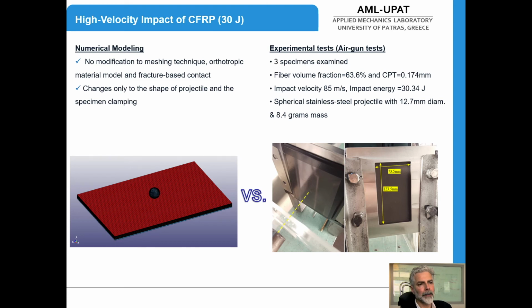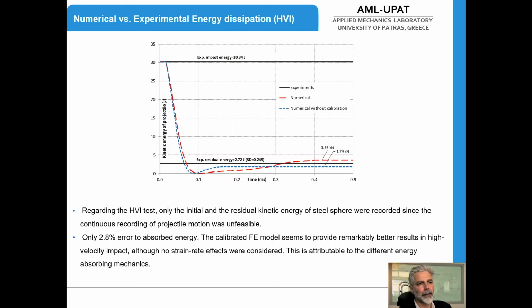This experiment has been made by using an air gun, and of course we have tried to simulate this experiment based on the same methodology that we earlier described, meaning that we use LS-DYNA explicit, we use 3D elements, we use the same optimized calibrated material parameters, and the only changes are the projectile and the clamping devices. Unfortunately, here we did not have the possibility to capture the contact force versus time plot. However, we can simulate the kinetic energy of the projectile, and we can see that the kinetic energy of the projectile is much closer to the results gained by the calibrated material properties.